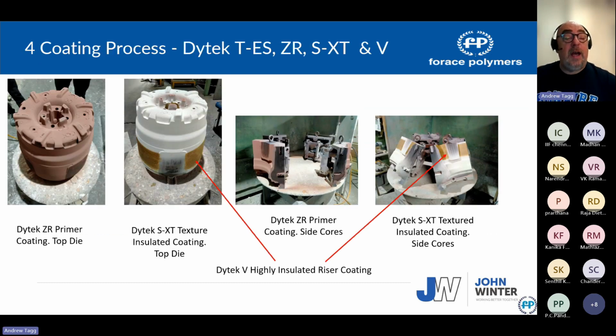So on the top die, which is this part here, there's the primer coating. It's red, so it can show through when the other coating is wearing. Then on top of that, the SXT, and this is built up to 800 microns, which is an insulated coating. And the reason for that, I'll explain in a minute.